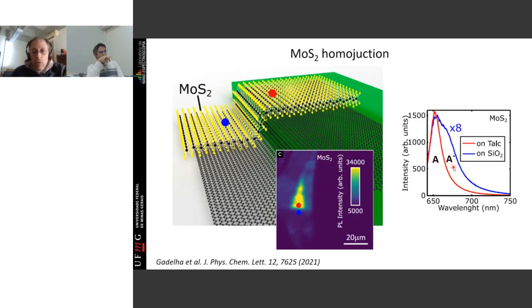Excitons is when you excite an electron, and the electron hole pair bind to one to another, and you form this entity that's called an exciton. And if you dope the material and you have a charge in the exciton, you have a trion, okay? And what we see is that the different doping ranges have a photoluminescence that is very different.